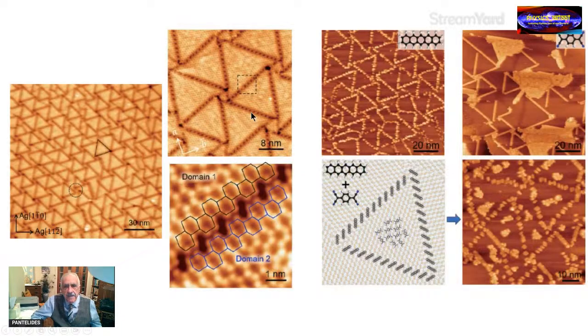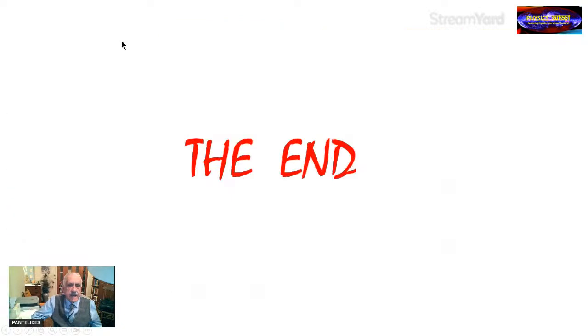And the last one we did, silver selenide, a very different pattern. And here is the boundary. If you use this molecule alone, pentacene, it goes right on the boundaries and forms these corals. If you use this molecule, it goes everywhere and forms patches. And if you use them together, you get the patches inside the corals. So another demonstration of selective patterning and selective process.